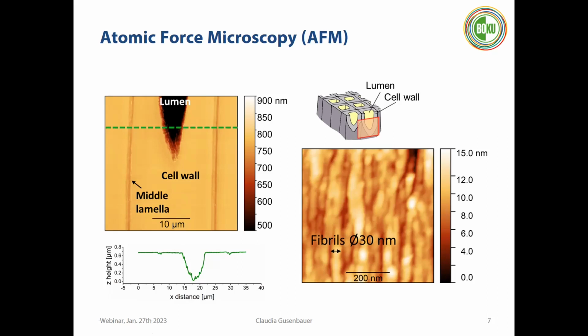And then the powerful thing about atomic force microscopy is that when we zoom into our sample, like here on the right side, you can see a zoom image into the secondary cell wall. We can already see the wood fibrils with a resolution of several nanometers. I think this image has a resolution of 2 nanometers, and we can nicely measure components like the wood fibrils of about 30 nanometers. So here you can see the advantage of atomic force microscopy, that with little sample preparation, we can already get a really high resolved image of the wood cell wall structure.